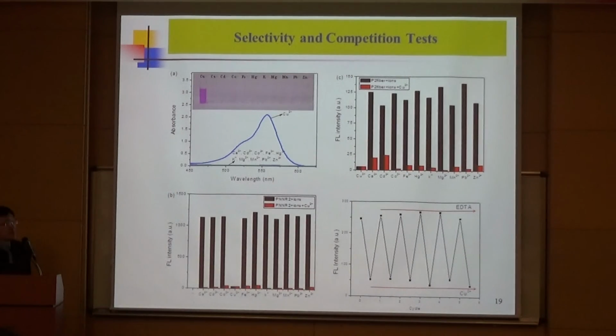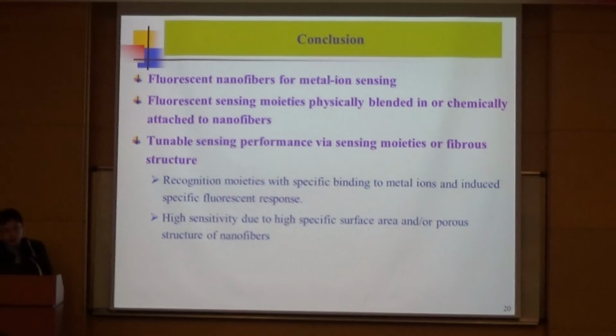And from the selectivity and competition tests, we concluded our rhodamine copolymer shows very good selectivity for copper ion, without interference by other types of metal ions. And again, our nanofibers could be regenerated through treatment with a chelating agent repeatedly for many cycles. So in conclusion, we demonstrate the application of fluorescent sensing nanofibers for metal ion sensing applications. The sensing moieties could be either physically blended into or chemically attached onto the nanofibers. The sensing performance of the nanofiber could be adjusted either through changing the chemical structure of the sensing moieties or through manipulation of the electrospinning technique.